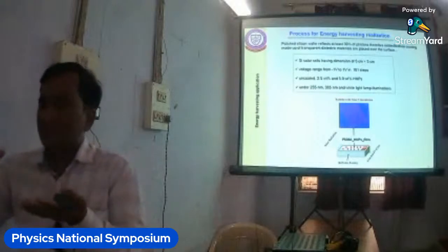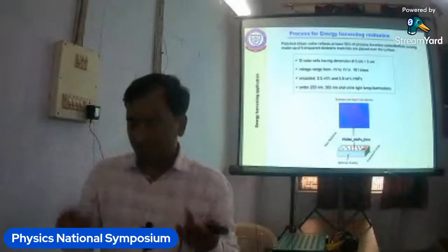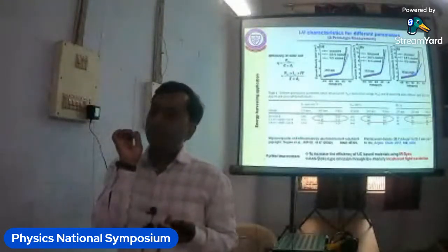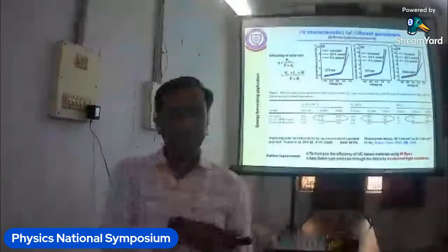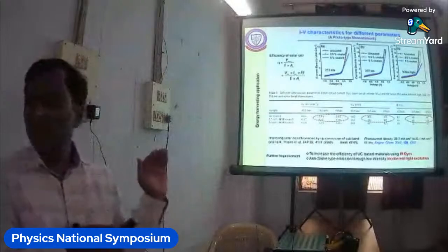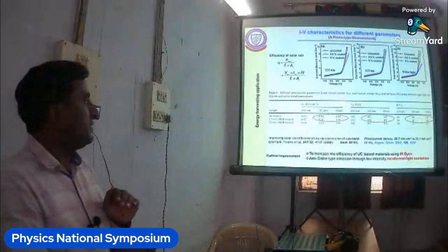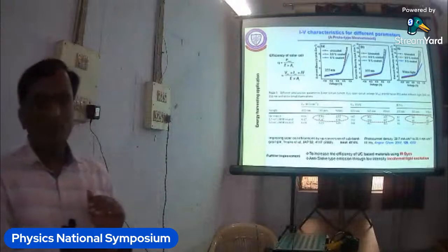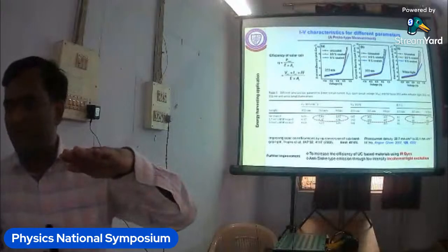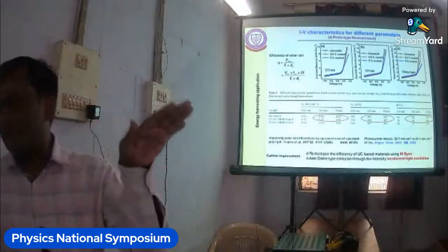So your PMMA is not absorbing anything. Ideally, I can say there is some absorption, right? Around 3 to 5% absorption is there, but 97% it is transparent in the region of interest, and your material will do all the things. Okay. Now, in order to see the conversion efficiency or to characterize any photovoltaic cell, there are three parameters that we have to see, and these three parameters are ISC, short circuit current, open circuit voltage, and fill factor. So what we did, we coated this film onto the surface of a crystalline silicon solar cell, and then we excited with different wavelengths and recorded these three parameters.